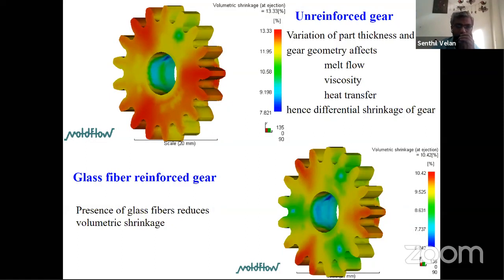So what is the challenge? This is about a simple polymer, but when you add reinforced fibers, you can see this difference. This is the unreinforced material, and this is the reinforced material. This is a simulation, though I will show the actual shrinkage values also. You can see that broadly it reduces the shrinkage, because what we have added is glass, which is not going to behave like a polymer. These are basically elastic materials, so you will not have shrinkage unlike your base matrix. So naturally you will have reduced shrinkage. You can see the value here, 7.82 to 13.33, and here it is 6 to 12 and so on. There is some drop in shrinkage.